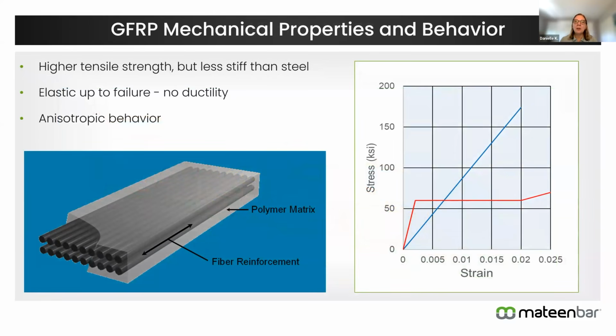So the GFRP mechanical properties are different than steel. It has a higher tensile strength, but a lower stiffness. If you look at the figure on the right-hand side, this is a very simple representation of that stress strain curve, the red line representing a grade 60 steel bar and the blue line representing a GFRP bar. So you can see that much higher tensile strength where that failure load is, but you can also see the slope of the line there representing that lower stiffness. It is linear elastic up to failure, and so there is a limited ductility. This is accounted for within the codes. And it is anisotropic, with those fibers going along the longitudinal direction of the bars. The properties across the bar or across the section are slightly different than they would be longitudinally. So a few things to consider during the design.